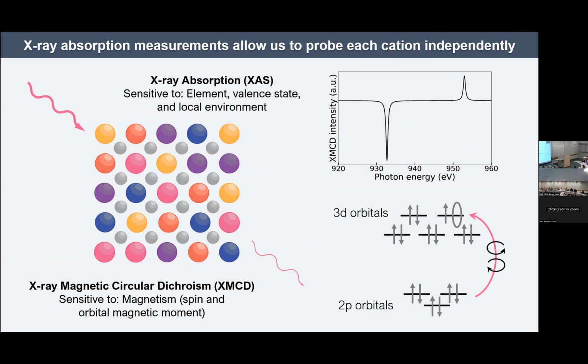So you measure this after you apply the magnetic field. The measurement is done with the magnetic field applied. So actually, we just have a little neodymium permanent magnet, and it's just near the sample. And so it only works if your sample is magnetically soft. Right. Yeah.